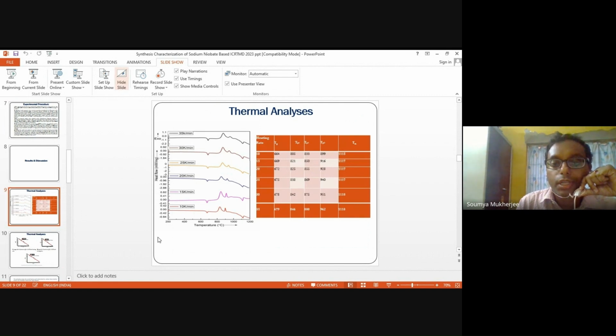Now, thermal analysis has been carried out at different heating rates, that is 10 Kelvin per minute, 15, 20, 25, 30, 35. And we have noted the corresponding glass transitions, the onset of the first peak, the peak maxima of the first peak, second peak, and the melting temperature. These variations which have been observed are mainly due to changes in the viscosity of the glass melt. The Tg is the change from the melt to the glassy state, and there is some viscosity change, and due to these viscosity changes within the matrix, these values are also changing correspondingly.